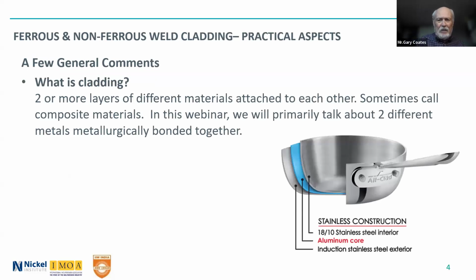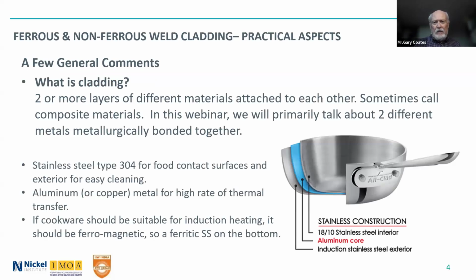And here, just a common example of a stainless steel pot, a high quality one, where you have, actually in this case, 3 different materials. You have type 304 for food contact surfaces, ideal for that, for the interior and exterior for easy cleaning and hygiene. You have aluminum or even copper for the high rate of thermal transfer. And if you're using induction heating, you want the bottom part to be ferromagnetic. So a ferritic stainless steel is used there.